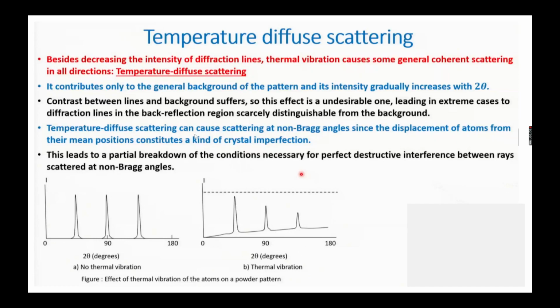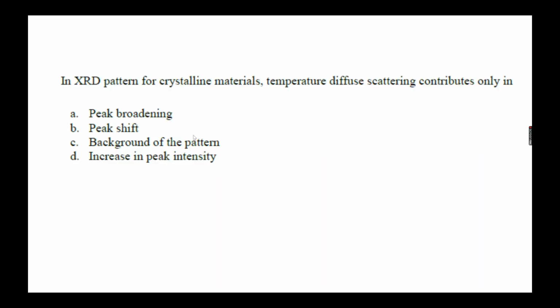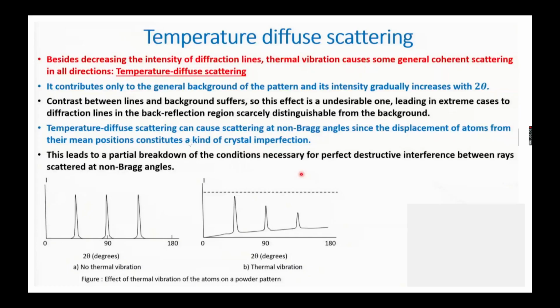That's why the temperature diffuse scattering contributes only in the background of the pattern, like this general background, and its intensity gradually increases with 2 theta. The contrast between lines and the background suffers. So this effect is undesirable, leading in extreme cases to a diffraction line in the back reflection region being hardly distinguishable from the background. So we have to set up the background, or subtract the background, in order to get our XRD peak in the same line.